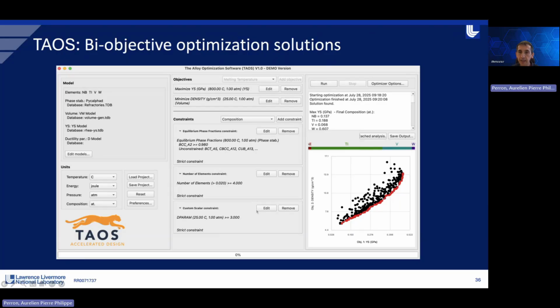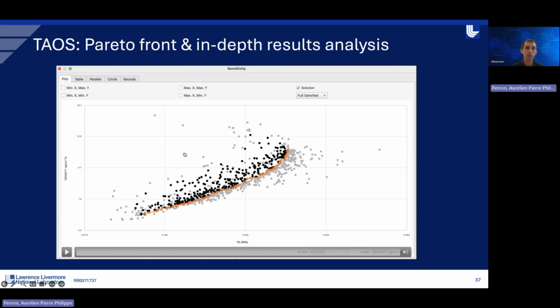You cannot see it here because it's a screenshot, but when you go over the points, it will tell you what composition and the properties of these alloys. But what you can also do is a more post optimization analysis. So when you click on that button, you can plot again the same Pareto fronts, so density versus yield strength, but you can plot different versions. And the orange points that you see here are the Pareto front. And the main difference between the black and the gray symbols is that the black symbols correspond to the constrained optimization. So that's, between quotes, where your solutions are fully satisfied. That's your problem. And the gray one is the unconstrained optimization.